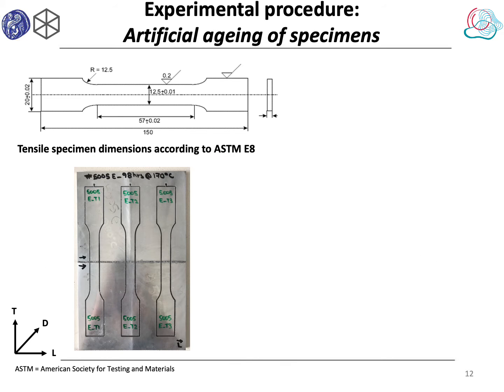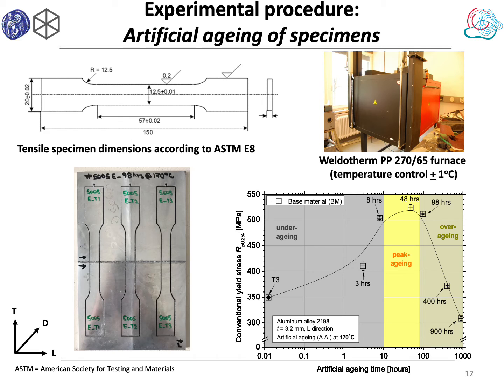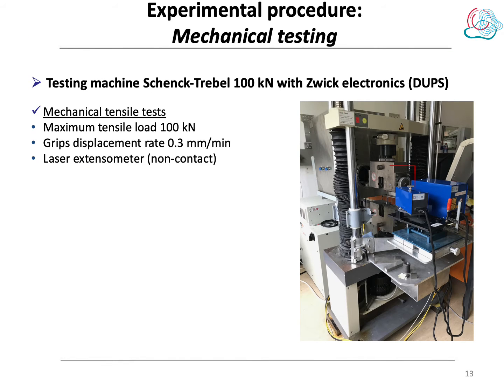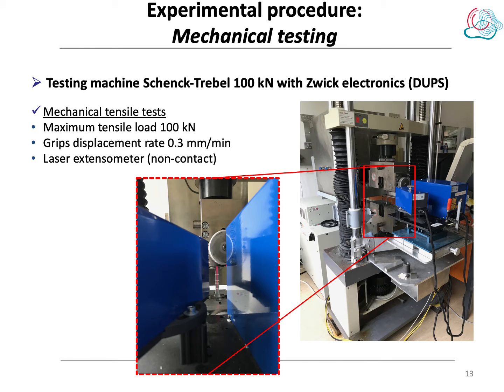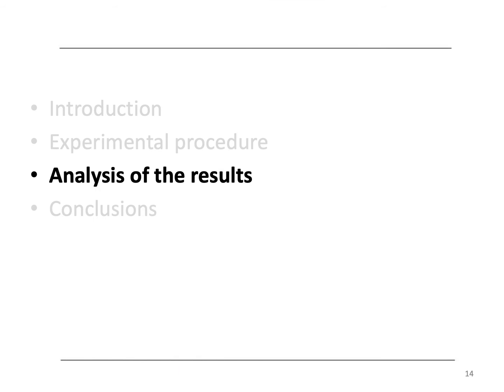This slide depicts the standard tensile specimen geometry according to the ASTM specification. The artificial aging heat treatments were performed in the furnace at 170 degrees and for 3 different artificial aging times, which were selected according to the literature, namely 3 hours, 48 hours, and 98 hours, in order to correspond to underaging, peak aging, and overaging conditions respectively. The mechanical tests were carried out at Helmholtz-Zentrum Hereon with a testing machine using maximum tensile load of 100 kN.